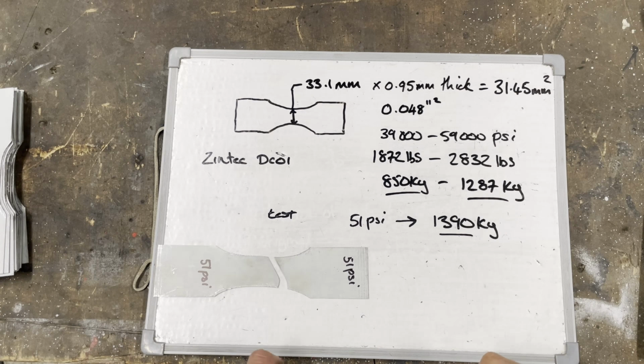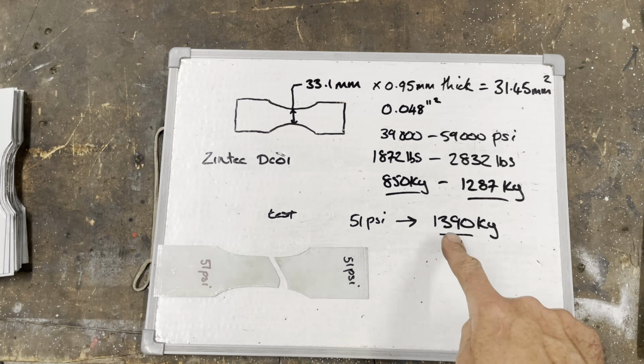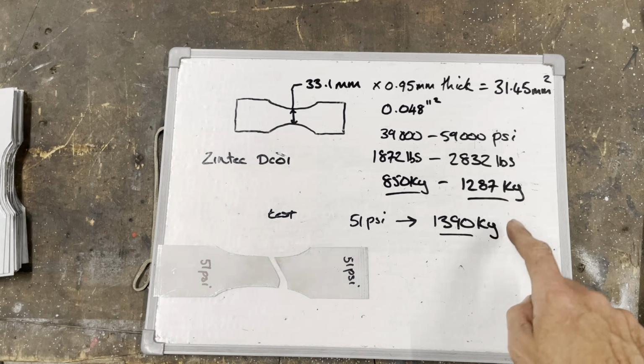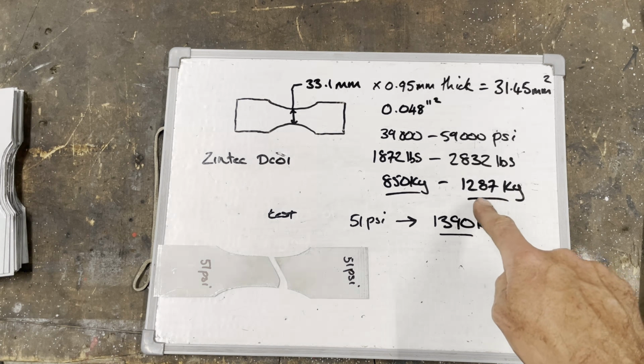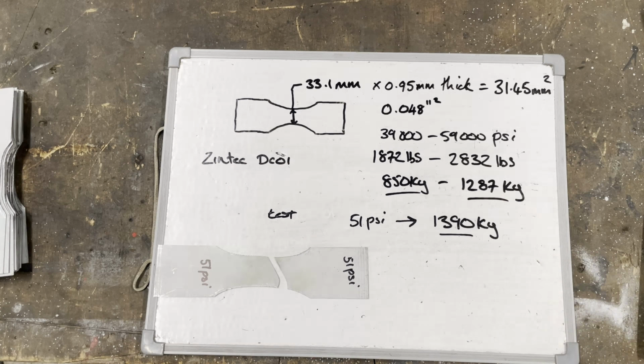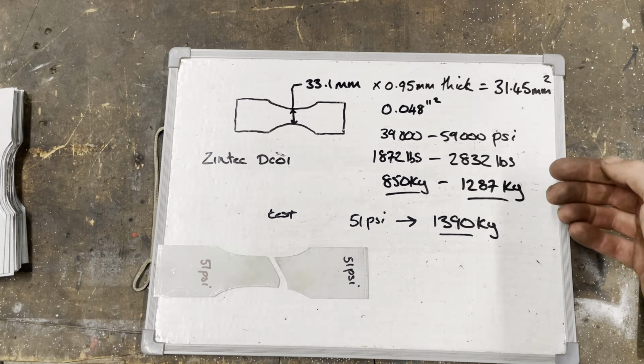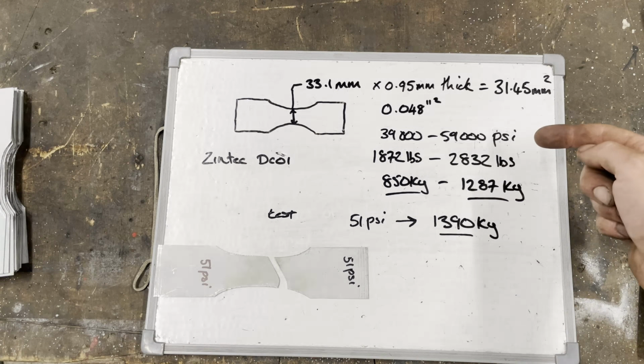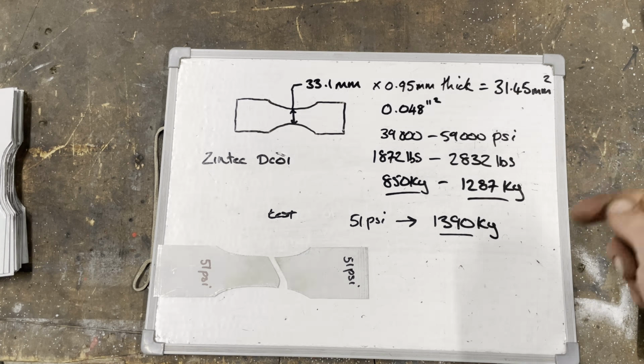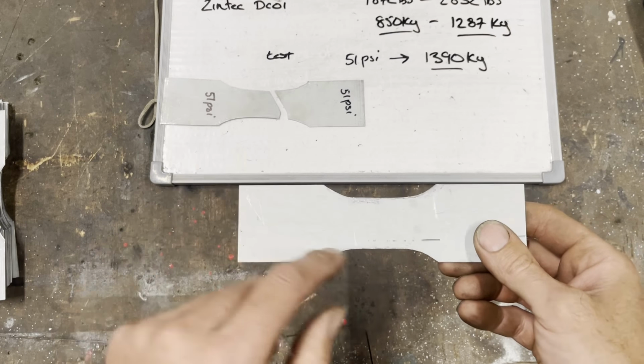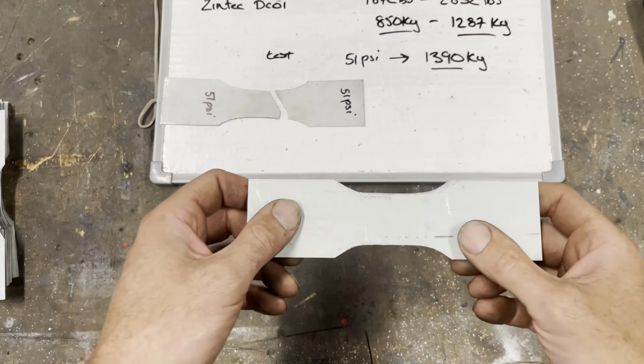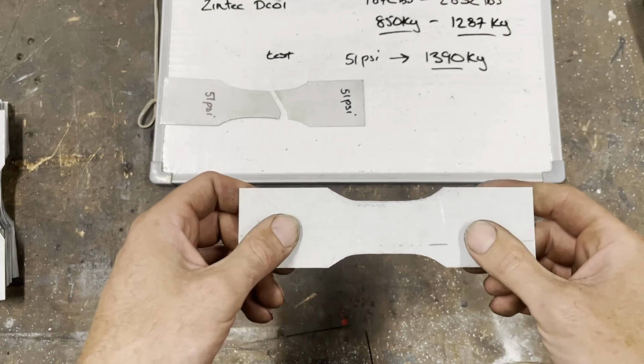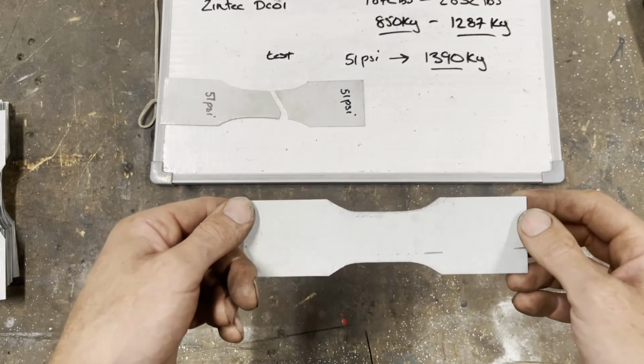That's our first test then. Broke at 51 psi hydraulic pressure, which is 1390 kilograms, slightly above the top limit of what I predicted, but I think that's close enough because manufacturers of materials tend to underestimate the strength of the materials just to be on the safe side. The next one then, I'll cut this in half with a guillotine. I'll weld it up via MIG butt welding, and we'll see what this breaks at.